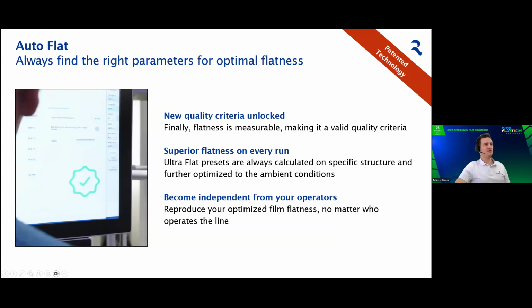So what we do now, we measure the flatness with a measuring device, with cameras. And by measuring it, we can also control it. So we have an auto control of the flatness, similar to the profile auto control. Everything can now be automatically adjusted, and you don't need an operator specially trained and set up for this. Everything can be done by the system.